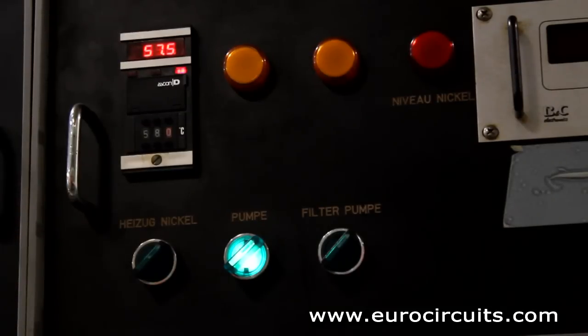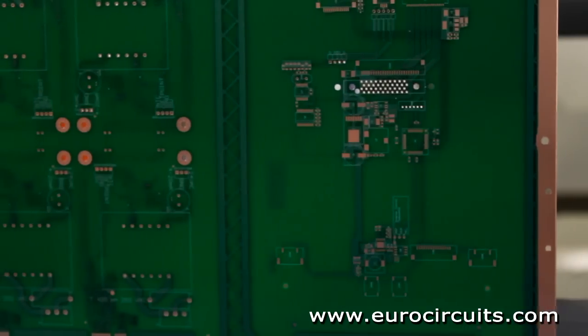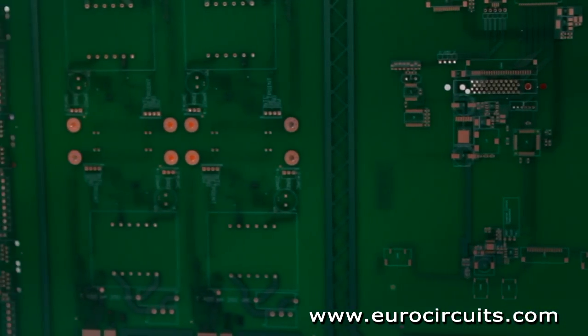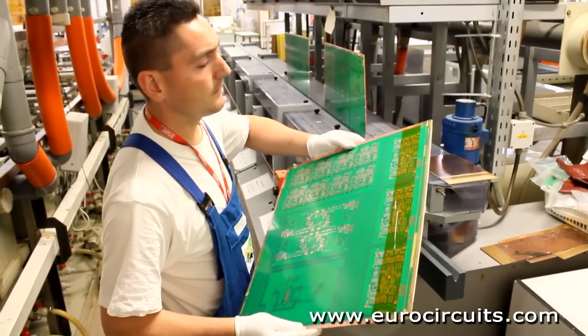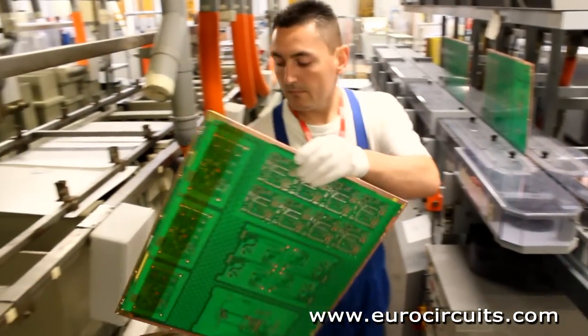For this you require a hard electroplated gold. For edge connectors we electroplate 1 to 1.5 microns of gold over 4 to 5 microns of plated nickel.